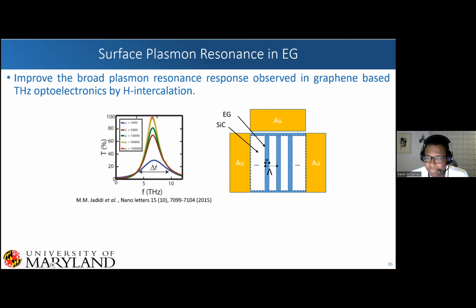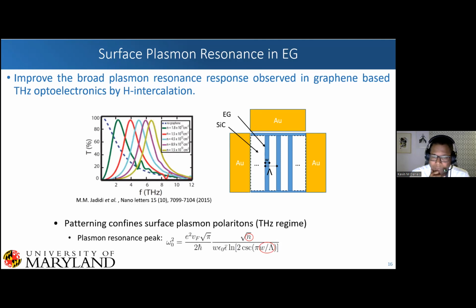We have some contacts here for gating, and we're really just making these ribbons. And the reason why we want to make these ribbons is because there are really 2 factors that can control what your plasmon resonance peak is. One of them is your carrier concentration. And so going from 10 to the 11 up to 10 to the 13, you can have huge shifts in your plasmon resonances, all the way to 8 terahertz, as shown here.